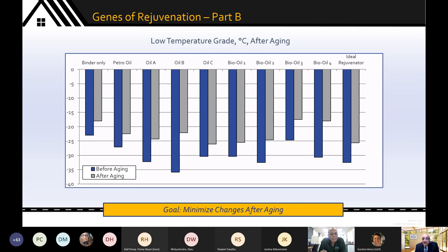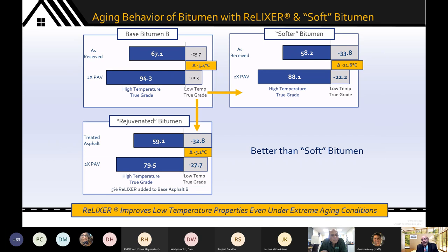By the way, this is the technical underpinning for the empirical observations of Anderson and company when they came up with their Delta TC. They looked at a large number of performing versus non-performing roadways and came up with a parameter called Delta TC. This lays the technical underpinning for that empirical observation. We spoke about Delta TC. What is it? It's a test that is performed on aged materials, PAV aged materials. It's tested using a BBR, a bending beam rheometer, and you're looking for the difference between the stiffness and the compliance, between the S value and the M value.